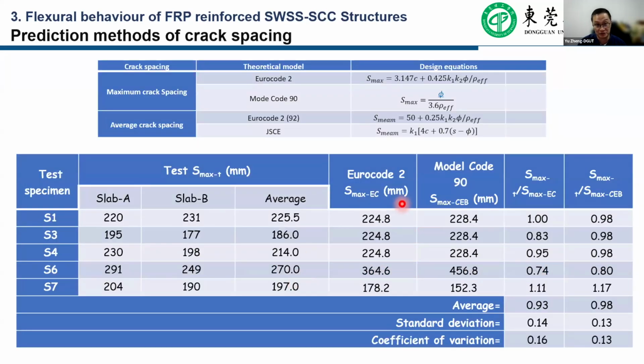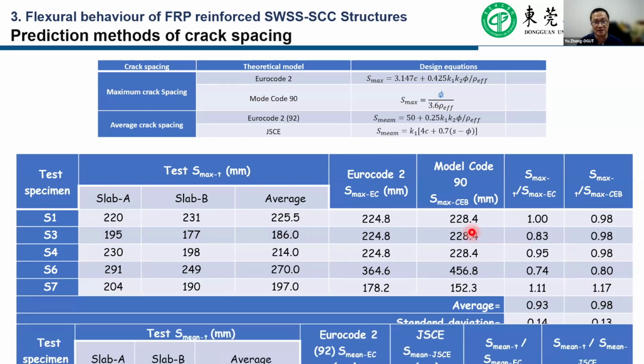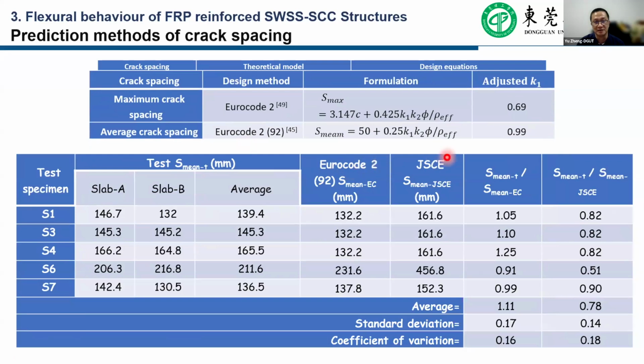Furthermore, we also extend the research to the crack spacing. For the maximum spacing, we use the Eurocode and Model Code 90. We can find the Eurocode shows the better prediction. Those two models have shown a good prediction of the maximum cracking spacing. But for the average cracking spacing, the bond coefficient needs to be modified. After the modification, we can use the Eurocode to predict the average crack spacing well. But the JSCE, the Japanese code, cannot give an accurate prediction.